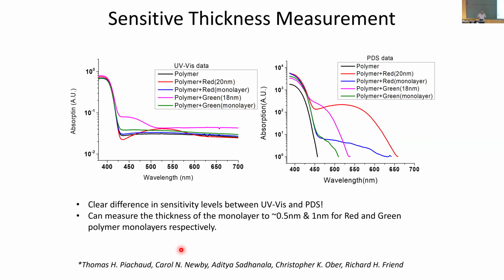To do that, you have a known thickness of a monolayer. This sample says 20 nanometers is a known thickness, and this red one is the supposed monolayer. This is a spectrum from a traditional UV-Vis transmission spectrometer, plotted on a log scale for clarity.